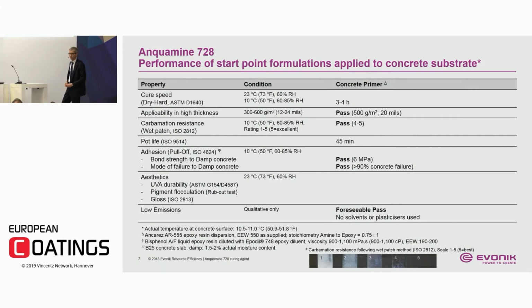And you see here some basic data, part of which I showed. You have a system of 3 to 4 hours cure. It's on 500 grams per square meter. A pot life of about 45 minutes. Good adhesion to damp concrete. So again, the thinking is not dry concrete, which is rather easy. It's the damp concrete which makes it quite challenging. The system will also cure to wet concrete, but I think that's less relevant. I mean, any applicator will tell you they will stay far away from the dew point in order not to get into trouble. And damp concrete is your best representative case for this.